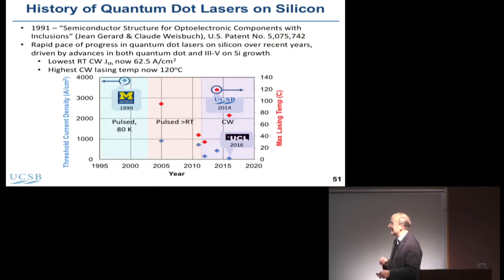The red dots are the maximum CW temperature. Again, in the early days, they wouldn't even run at room temperature. Now in CW, you can get them running up to 120 degrees C. So that's probably adequate for almost any application. Obviously, silicon electronics is going to run at certainly 80, 100 degrees C. This is marginal, but the highest temperature lasers are all quantum dot lasers. And so that's the focus.